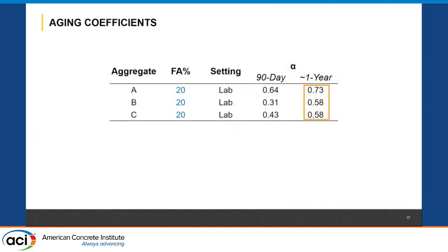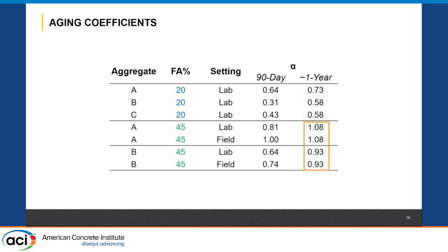At 1 year, I did a bunch of retesting and I found great correlation at 1 year that was not present in 90 days. If there are any researchers here, you know that when you get 2 decimals of similarity, you right away are like, that can't be right. And I ran the numbers like 10 times, and they were right. And they were right for 2 other sets of mixes.